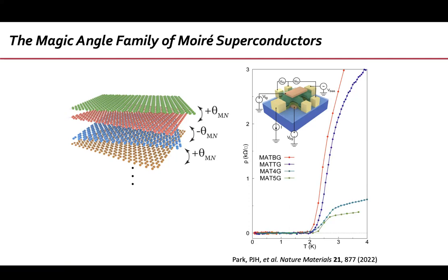The true answer is that we do not understand superconductivity and its strength in these superconductors, so I cannot give you a detailed answer of why it exactly compensates. But when you look at the Fermi temperature and the densities, these are always a fraction of an electron per Moiré unit cell. The Moiré unit cell is changing a little bit, so that changes the Fermi temperature a little bit. The effective mass changes a little bit, because although this flat band is there, it's not identical in all the structures. Somehow they combine in a way that doesn't deviate too much, and each of those terms doesn't deviate dramatically.